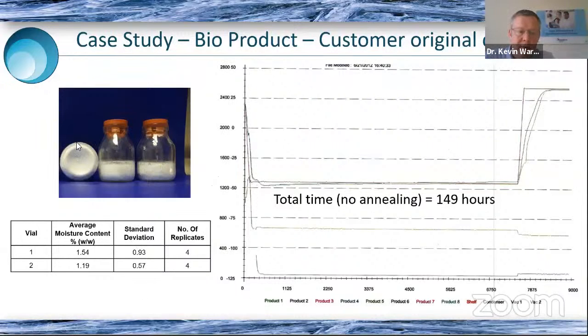Actually, the product didn't look too bad. It's in these relatively short molded vials with quite a high neck size. So in terms of impedance to vapor flow, it's not too bad. And the customer is achieving a relatively low moisture content, and they were very happy with that. But they weren't really happy with the length of the cycle. It's nearly a week, it's a 6-day cycle. And so the first thing we did was to say, well, now we know that annealing the product is going to increase its collapse temperature. The first thing we're going to do is apply an annealing step.